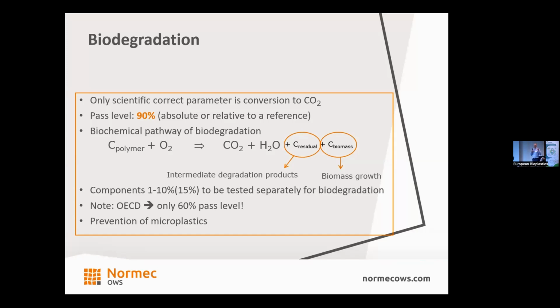Now, let's get a few more words on biodegradation. Biodegradation for us, the only scientific proof and the correct parameter is the conversion of the carbon into CO2. It's not a reduction in molecular weight. It's not a carbonyl index. That can be the first sign, but it's not a proof of really final, complete biodegradation. The pass level that should be achieved is 90%, absolute or relative to a reference material.